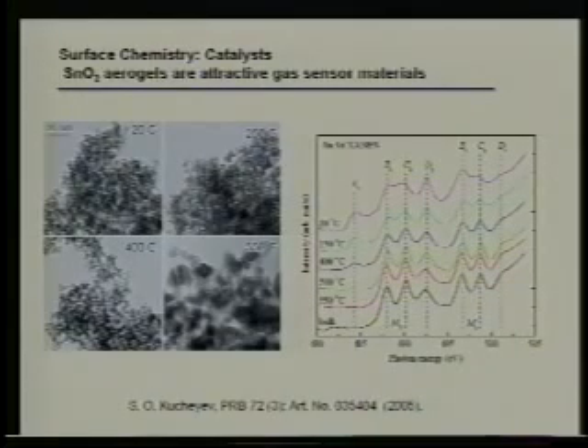So my first example is in the field of catalysis. And what I'm showing you here is a tin oxide aerogel. I'm not sure how many people know what aerogels are, but to first approximation, an aerogel is solid smoke. The densities are 1%, less than 10% down to 1% of the full density. You can hold them up, and they're transparent in some cases. And what I've shown you here is a tin oxide aerogel, which is an attractive material for gas sensors.